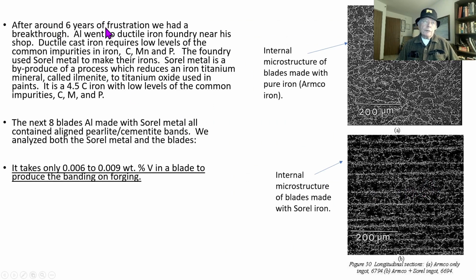After around 6 years of frustration, we simply couldn't make it work. We had a breakthrough, and it was due to Al. He went to a ductile iron foundry near his shop. Ductile cast iron requires low levels of the common impurity elements in iron: carbon, manganese, and phosphorus. The foundry uses sorel metal to make their irons. Sorel metal is a byproduct of a process which reduces an iron titanium mineral called ilmenite to titanium oxide, which is used to make paints. So it's a commercially viable process.